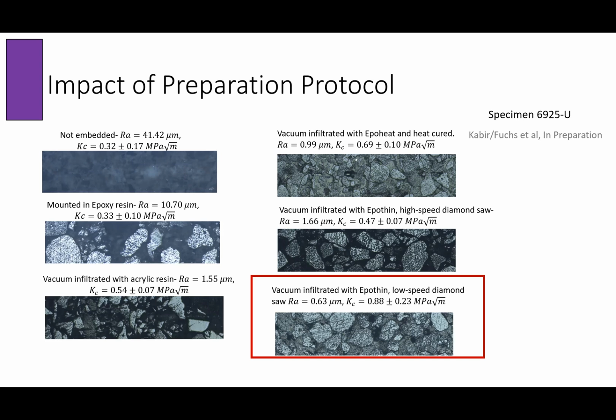So what you can see is that when you have a good preparation protocol characterized by a very low surface roughness, 0.63 micrometer, this is where you have the highest value of the fracture toughness, 0.88, which again agrees with tabulated values for rocks in the order of 1 megapascal square root of meter in the literature. So it's really important that all the samples are prepared in a very good manner, and that is really a strong quality protocol.